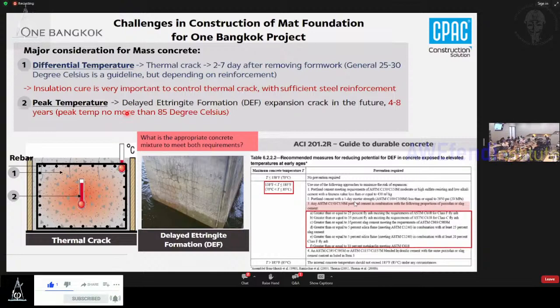Another thing we have to be concerned about is the peak temperature. For this project, we talked a lot about what number we should use for the peak temperature. Otherwise, if we don't consider this, we're going to get what we call DEF in the future. So we tried to get literature, and we sat together and figured out what number we should use. Some recommendations say that if you use fly ash in the concrete, you can limit the maximum temperature to around 85 degrees Celsius. So we talked about this number for this project.